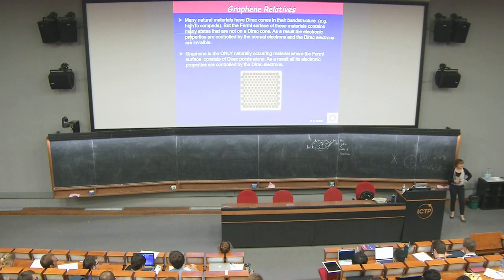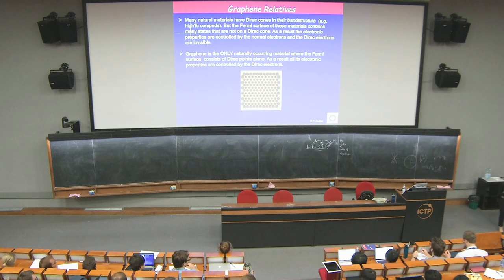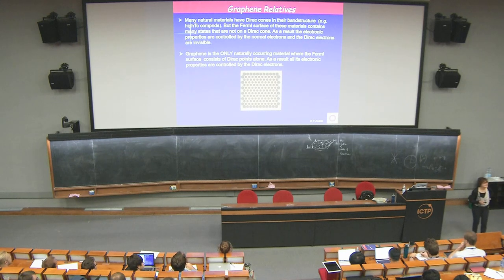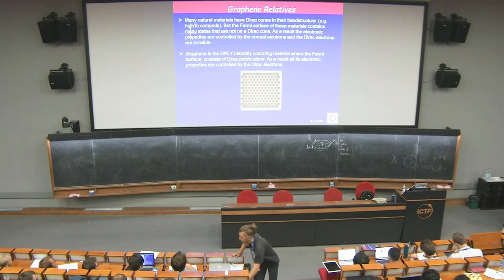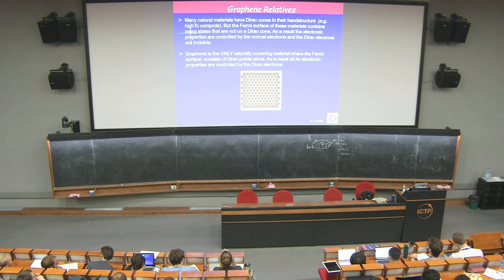So you might ask, what's so special about graphene? Why can't we do the same thing? Why don't we see it in other materials? In fact, Dirac cones are all over materials. Many, many materials have Dirac cones — high-TC materials all have Dirac cones in their band structure. The difference is that unlike all these other materials, in the case of graphene, there's nothing else at the Fermi energy except the Dirac points.